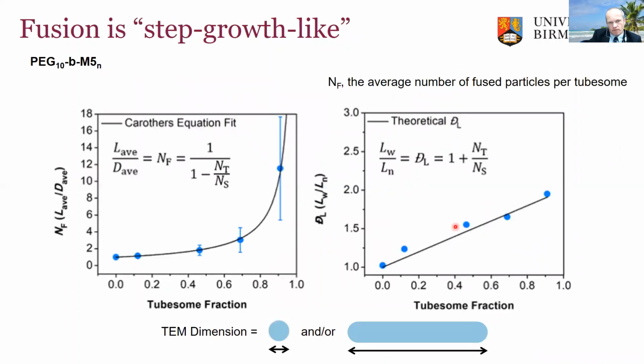And this fusion process is a step growth-like process, which is the growth process we might expect. So we can fit to the Carothers equation, using just dimensions from TEM. We can look at the Lw over Ln of our systems and theoretically predict the values we might expect, and it matches very well with the theory, indicating that we do indeed have this step growth-like process and growth of tubosomes.